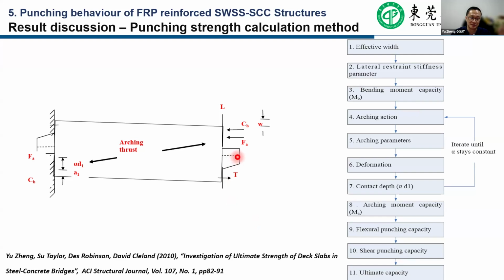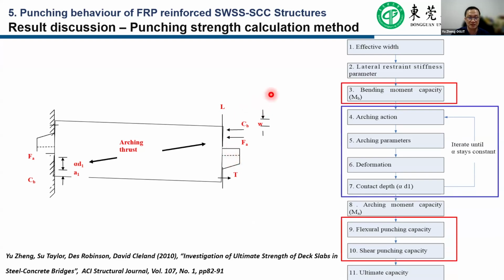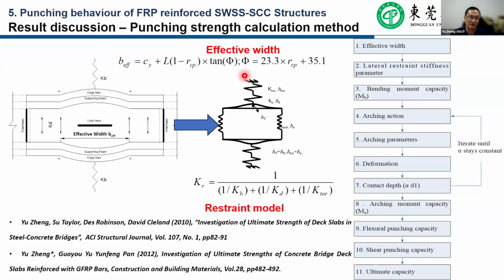Because of the arching action, the height of the compression zone can be increased compared to the bending prediction. This model is for steel reinforced concrete bridge deck slabs. Therefore, with this method we consider both the flexural punching behavior and the shear punching behavior in this prediction. Furthermore, the first part also establishes the effective width, considering arching action inside the concrete, and quantifies the external restraint stiffness. These first two parts of the prediction can be found in this journal paper.